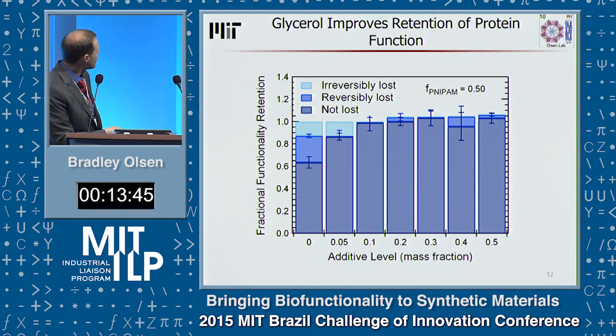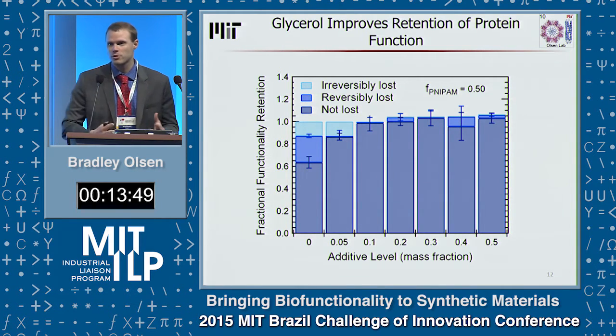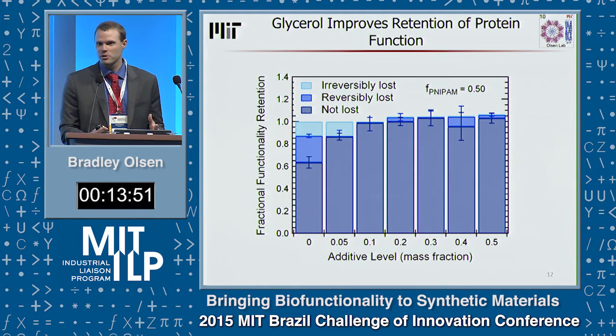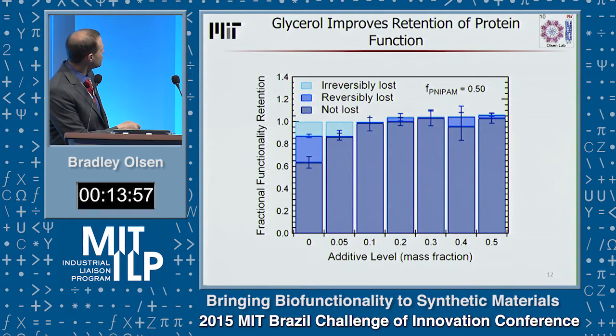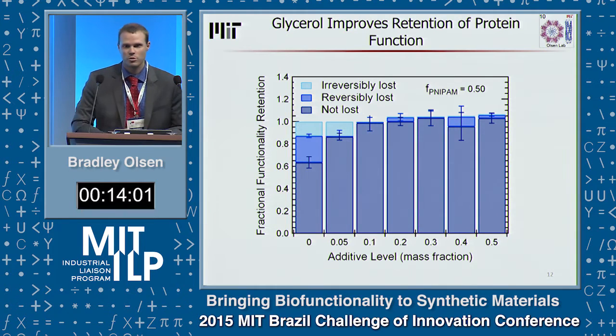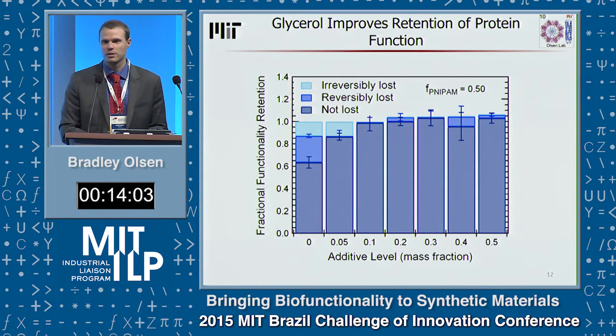And what we show here is that with the addition of small fractions of additives, in the pharmaceutical industry it would be called an osmolyte. In the polymer industry, we'd call it a plasticizer. But if you add a small amount of these plasticizers, you can actually maintain 100% of the function of the protein in the final material in many cases. And so you can really retain almost everything in its original functional form.